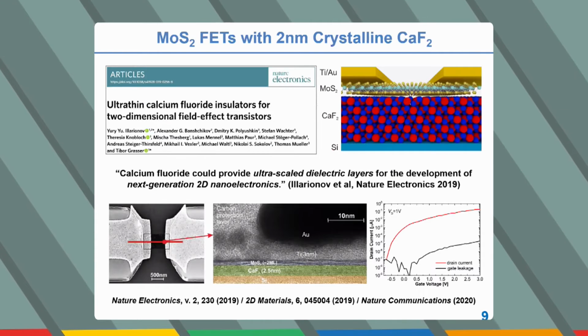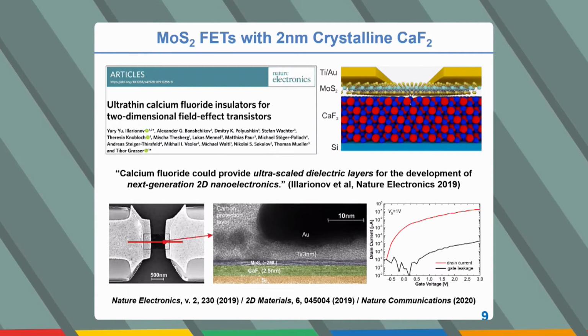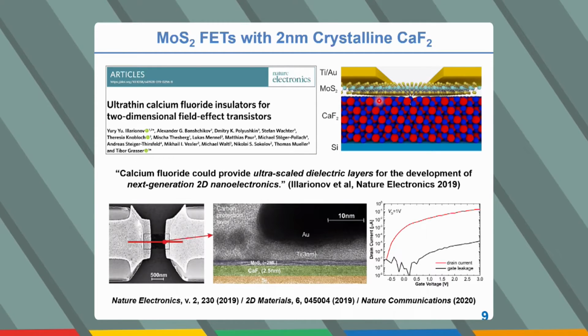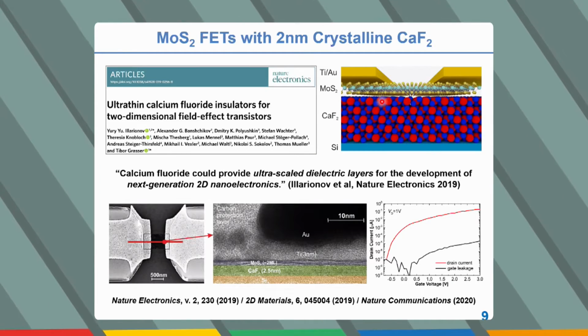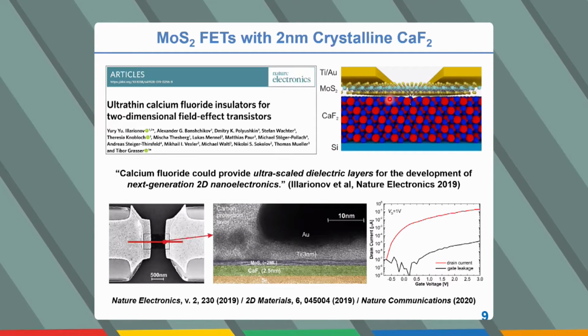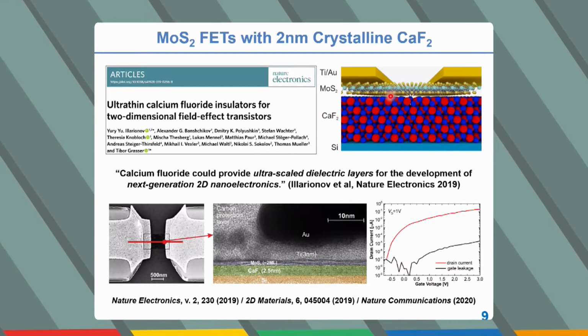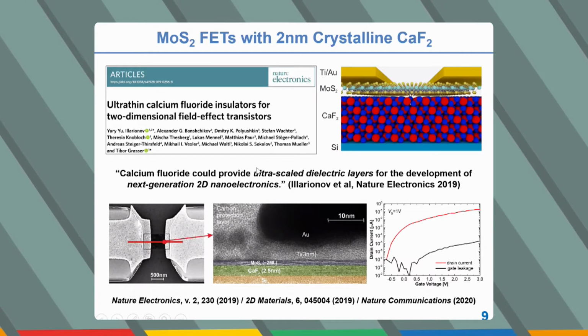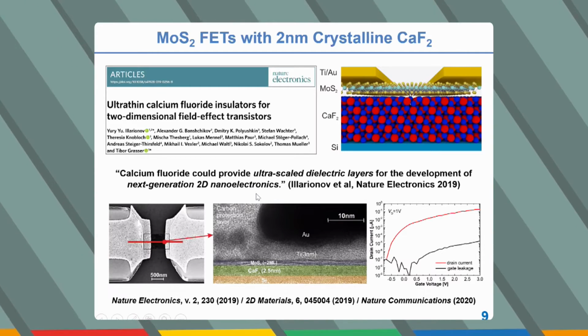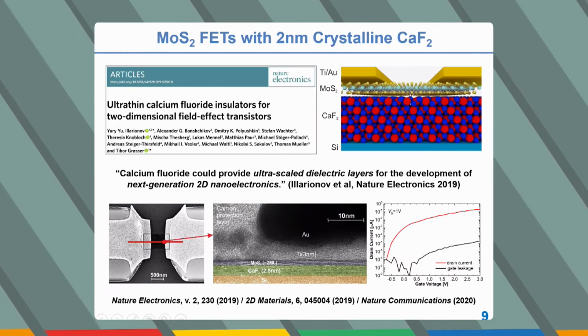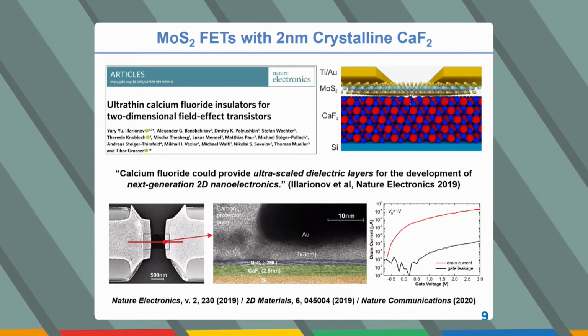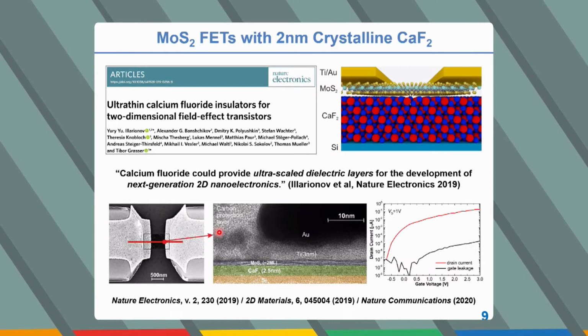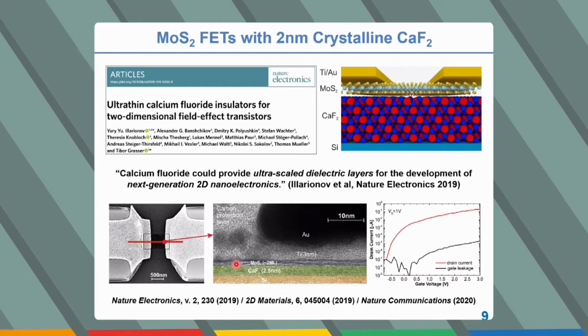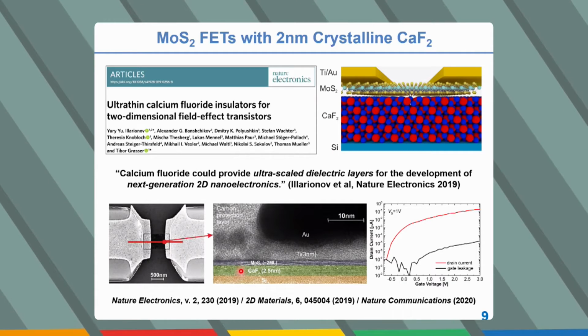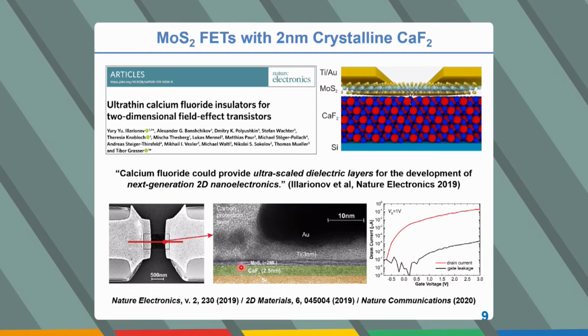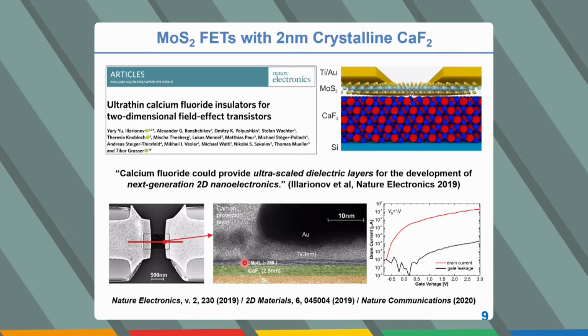And recently we took 2 nanometers thin calcium fluoride and transferred MoS2 of 1 or 2 monolayers on top of it, and demonstrated working devices, field effect transistors, which are world record thin, published this in Nature Electronics. And indeed, calcium fluoride could provide ultra-scaled dielectric layers for the development of next generation 2D electronics. We performed analysis of the devices, did SEM and TEM measurements, and indeed you can see that calcium fluoride is just 2.5 nanometers and 2 monolayers of MoS2 on top.